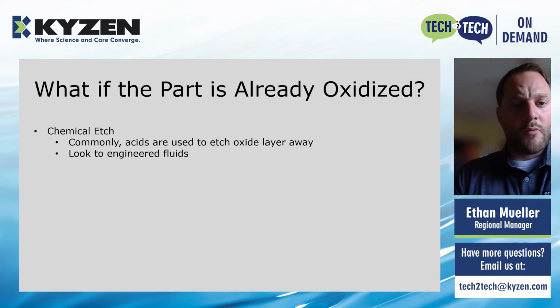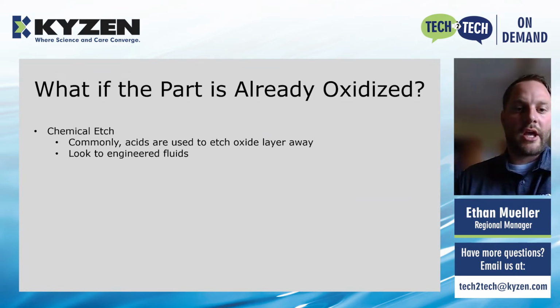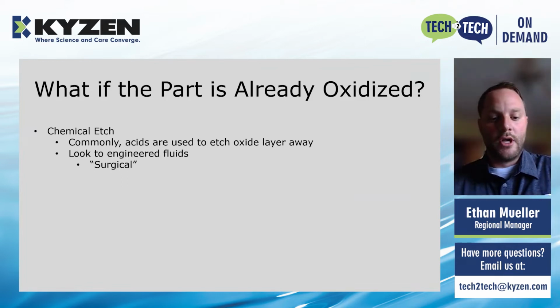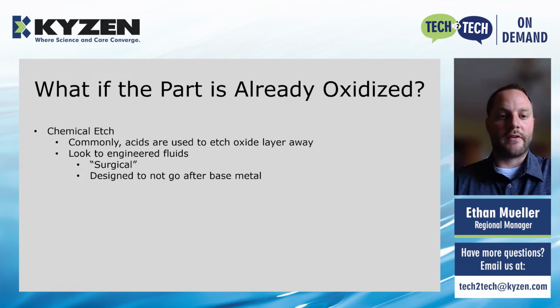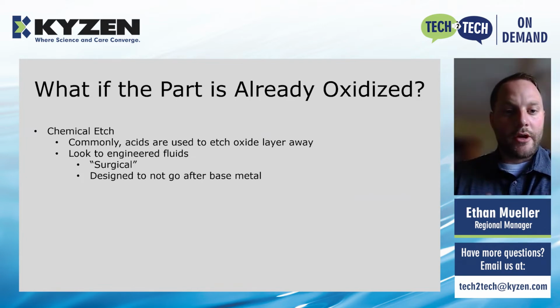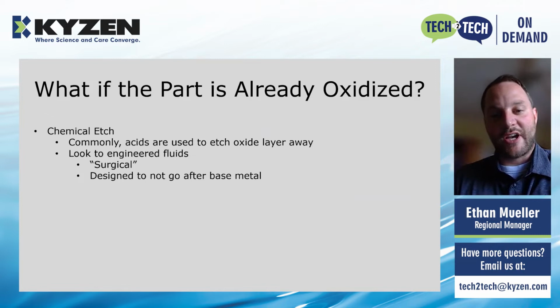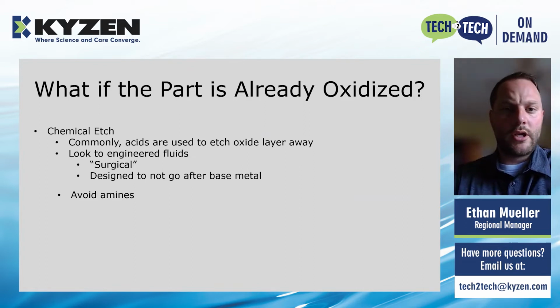When you're looking to do a chemical etch, it's good to look at some engineered fluids as opposed to just raw commodity type things. These are what I'm going to call more surgical. They're designed to not go after the base metal, and so you're more focused at removing that oxide layer as opposed to going in and impacting your base metal. With engineered fluids, if the exposure time is too long, you probably will start to go after your base metal, so you do want to be careful with that. But these fluids are developed for this exact process, and they tend to have more of a soft touch, or again, they're more surgical, if you will.